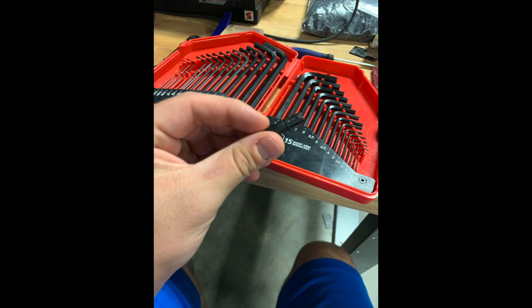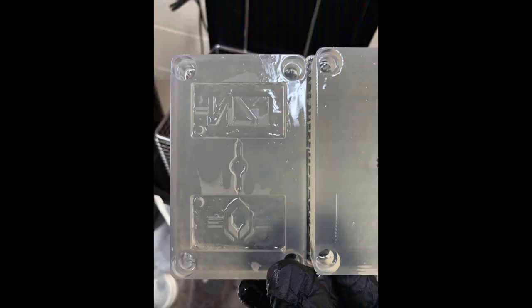We noticed some plastic cooled and dried in the machine. George had to remove the injection nozzle forcefully using a screwdriver to force the plastic out. This may be a result of our gates curing too early. To solve our problem, we filed down the gates so that the molten plastic could flow more freely.